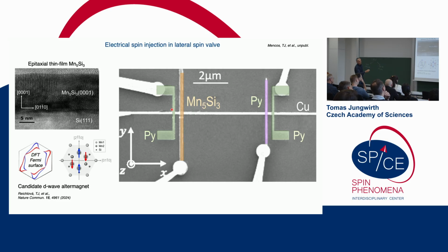Could you quickly clarify why this is a D-wave? The picture there? I couldn't see the rotation that I can do to get the spin up to the spin down. Yes, it's actually a twofold rotation. So you don't necessarily have to have a fourfold rotation connecting the opposite sublattices in a D-wave. You can have a twofold. When you do not have a 90-degree angle, but you have, for example, a 60-degree angle, you do this, right? Yeah. So it's a rotation axis along this nodal. Okay, got it. Thank you.